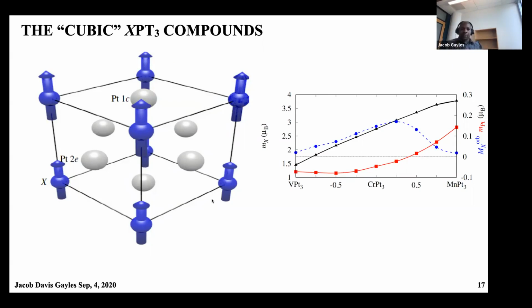And here what we did is we carried out some DFT calculations to calculate the total magnetic moment, shown in black, which shows the increase as a function of chromium into vanadium and chromium into manganese. We also calculate the orbital moment and the moment of the platinum. And here, the moment of the platinum actually changes sign, which becomes important for the mixing of the Berry curvature and bands.